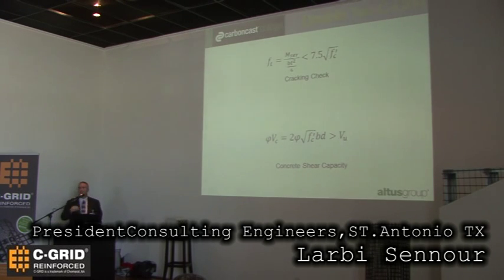For cracking, as you said, our codes got away from checking the crack width and all that. I know the Eurocode does that still, but in our codes we don't do that anymore. So what we do, we limit the tension to the cracking. Our cracking limit is 7.5 square root. Eurocode has a different one. But if we limit this, then we are crack free. We don't have to worry about crack width.